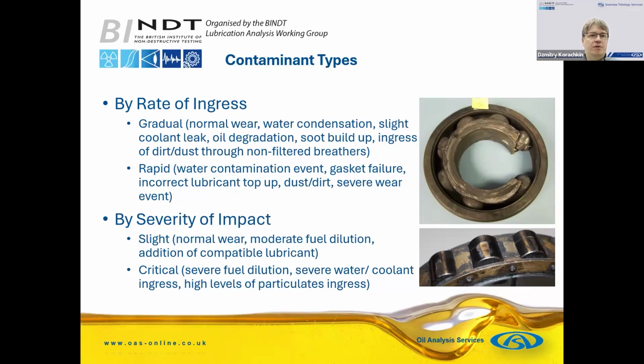But you can have critical impact as well. So severe fuel dilution reduces viscosity, can cause rapid wear of your engine, severe ingress of water or coolant. Again, the lubricant layer is broken down, oil is unable to carry the load between the loaded surfaces, and you can have critical consequences of that. And high quantities of particulates getting in, again, that can act as an abrasive component, causing severe wear and rapid failure.